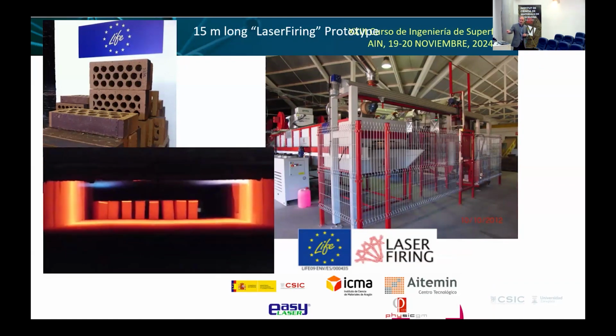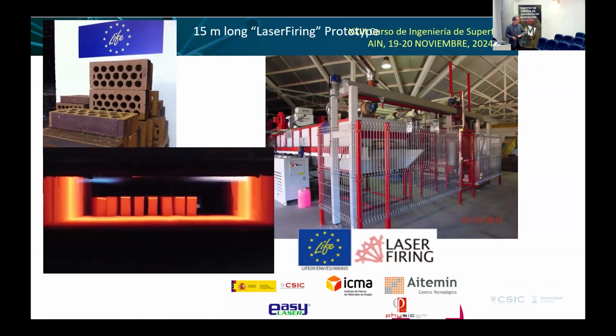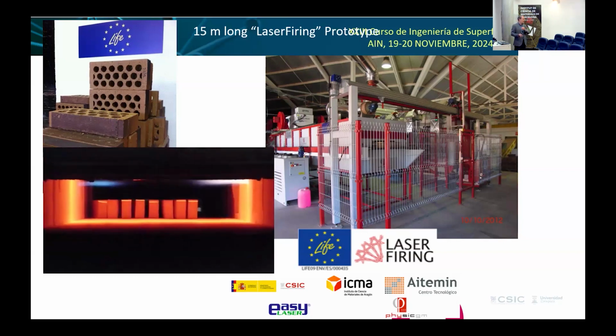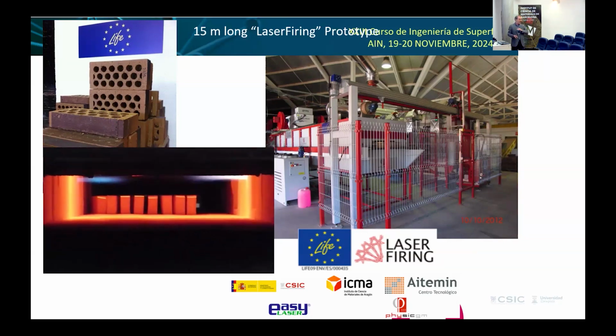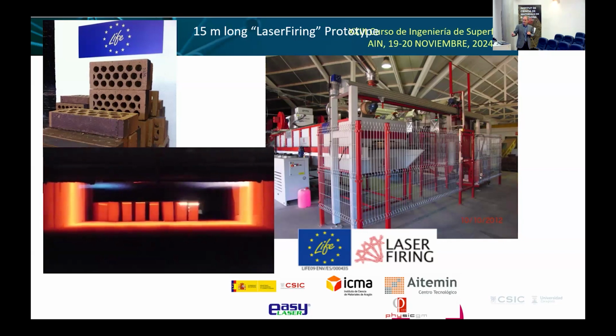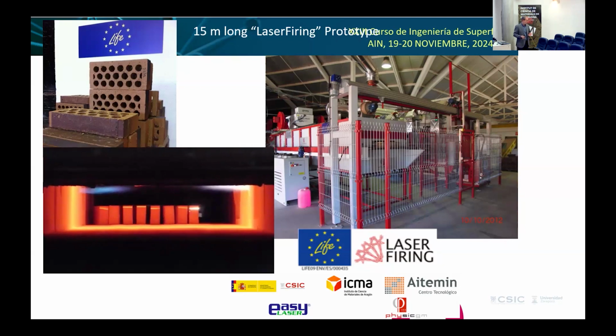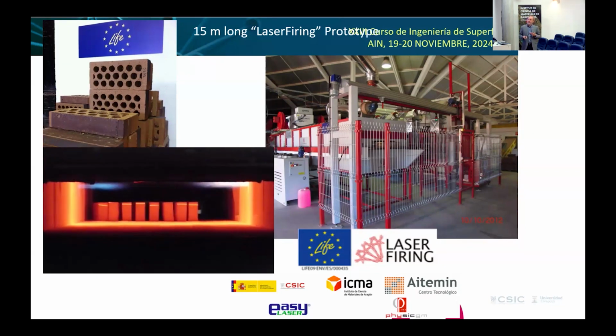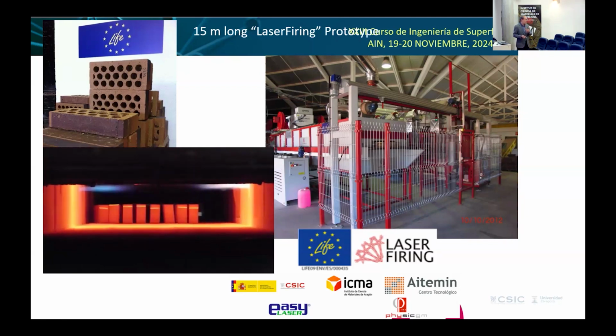So there's a line which covers the whole furnace, and all the bricks, although they are misaligned, are still very uniformly treated, as you see up here. And so we seal the surface of the brick. We did this because brick has very low value. We did not want to give the technology away. Although we had patented it, we wanted to preserve this.